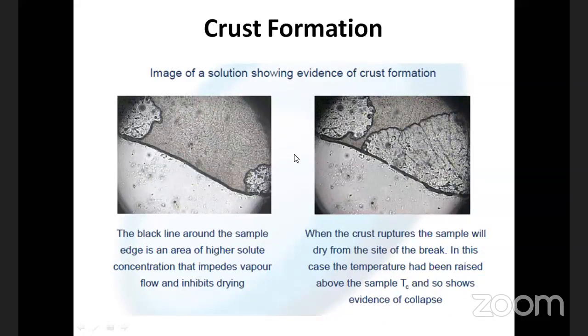Crust formation is a very important state during the drying of material in freeze drying, because this crust prevents liberation of vapor from ice, so that the material can remain in a dried stage. This is an image of a solution showing evidence of crust formation. This is one image where there is a crust, the dark portion; this line shows the crust that is formed. It blocks the vapors that are formed during the process of sublimation inside the crust. This second image represents the breakage of this crust, releasing the vapors that are present in the frozen ice.